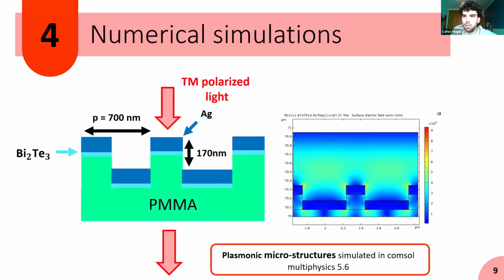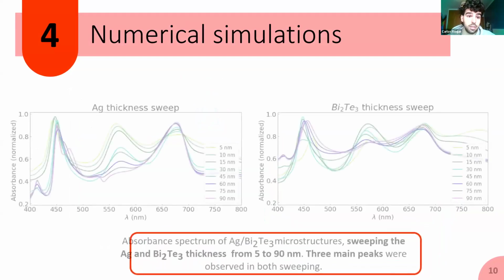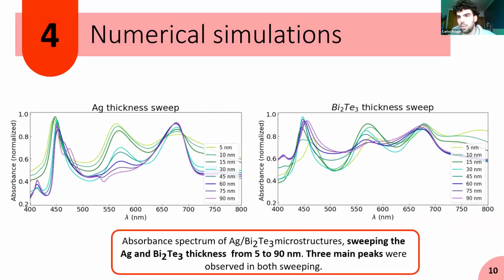Then we did some numerical simulations because plasmonics is really dependent on geometry parameters. We want to sweep some geometrical parameters, mainly the thickness of the materials, in order to observe the difference in the optical spectra and in the plasmonic response. We swept the silver thickness and then the bismuth telluride thickness. In the silver is where the plasmon is being excited, so most of the plasmonic events should be focused there. But in both of the sweeps, we identify three main peaks that we believe come from the plasmonic events. And as you can see, there is frequency shifting when increasing both of the thicknesses.